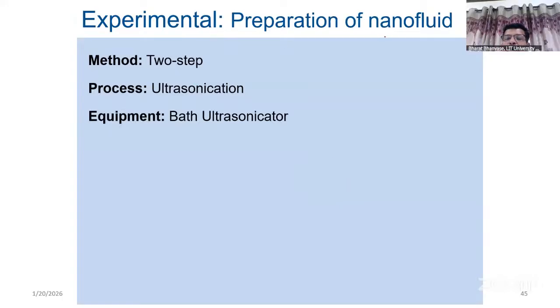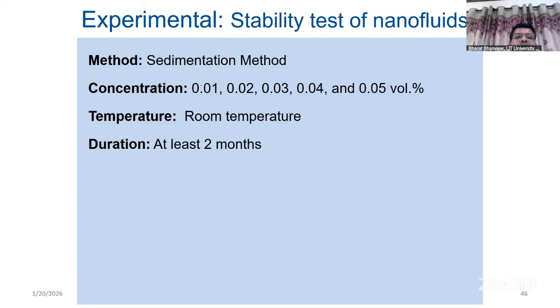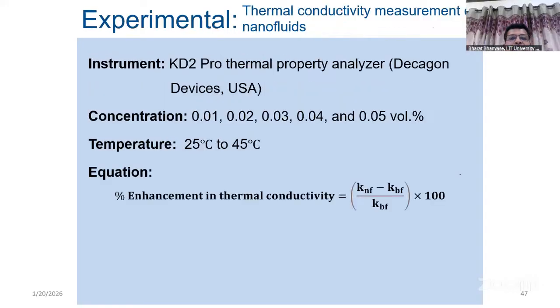Nanofluid preparation was done by the two-step method, because the Ag doped Fe3O4 nanoparticles we prepared were dispersed in water with the help of ultrasonication, so it is well dispersed in water. Then we carried out the stability test using the sedimentation method. For that, differently concentrated nanofluids were prepared, and that step was carried out for 2 months, with photographic evaluation.